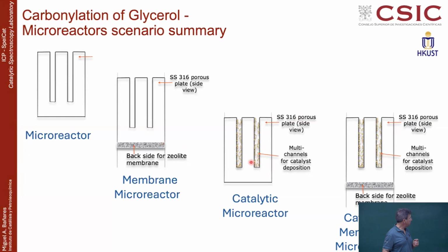The other option is to say, okay, I put the catalyst on the porous stainless steel, but no filter down here. Okay. And then you can get the complete package. You can put the catalyst in the channels and the zeolite at the bottom. In that case, it should be ideal because you have the catalyst that is doing the job and the filter, the zeolite, that will help you filter out the ammonia and go beyond the equilibrium.